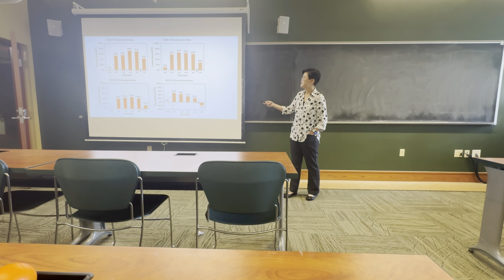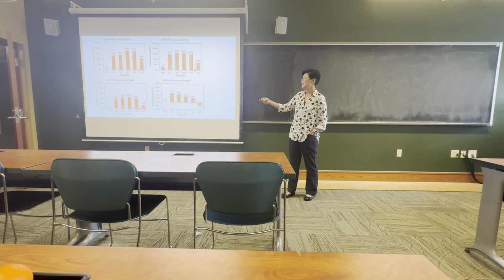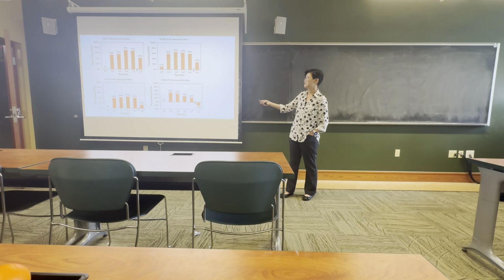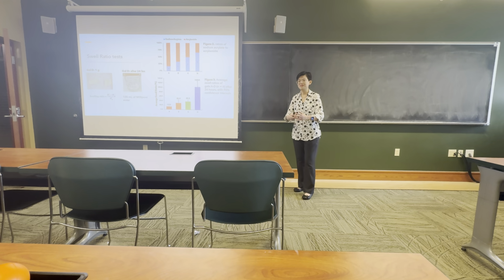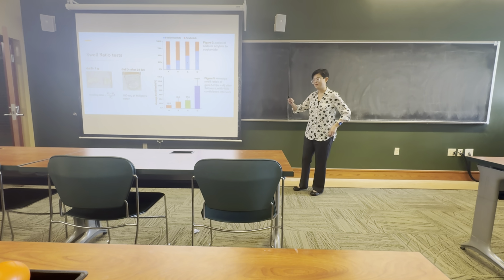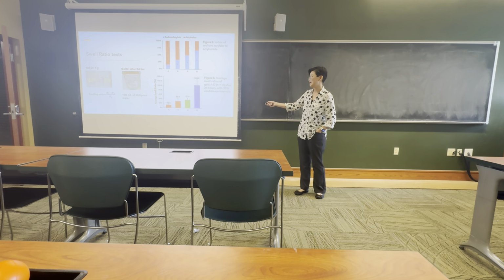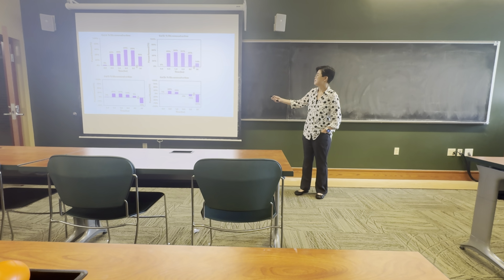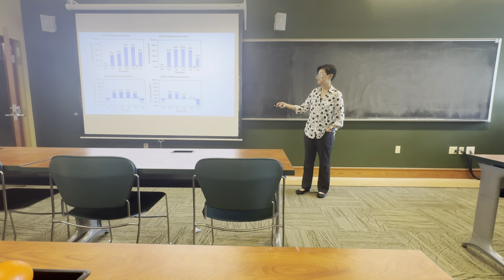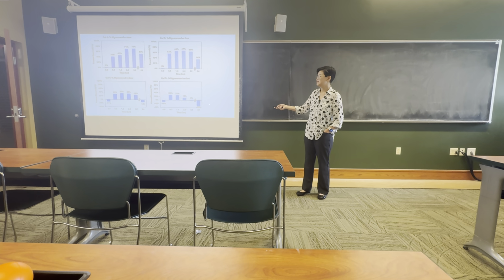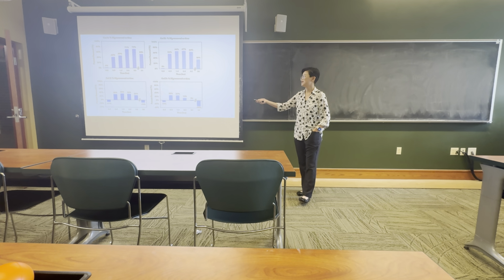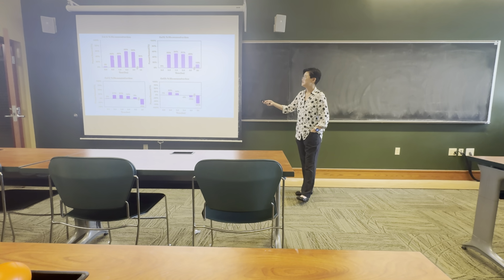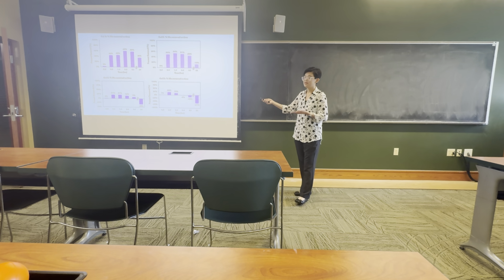Okay, and you can see that A and B appeared to remove more than C and D. Going back to the swell ratio, D has a greater swell ratio, which means the network is going to be expanding more, and so it might not be able to hold on to those ions as well as A or B. Okay, and magnesium shows a similar trend, and then these bars underneath the y-axis, I'll address them later. That was another issue that popped up. Okay, manganese: A and B performed pretty decently against manganese.